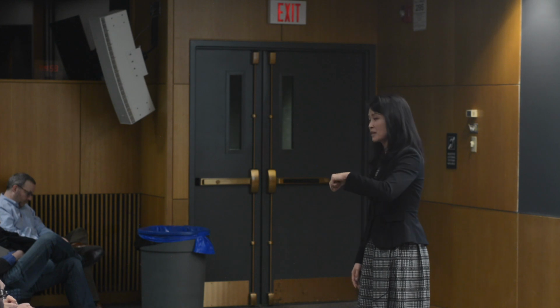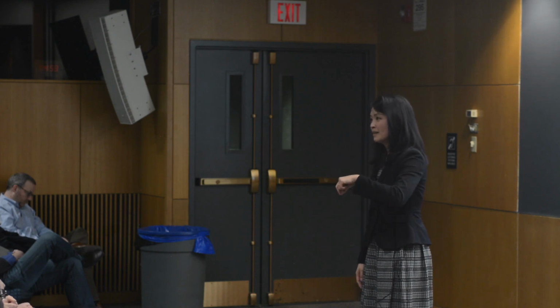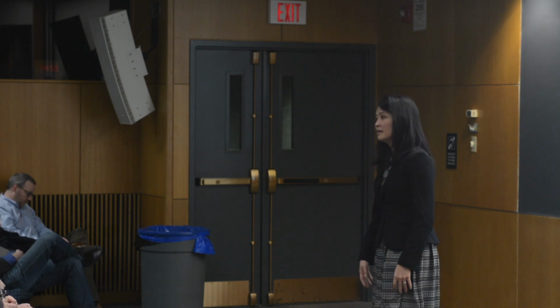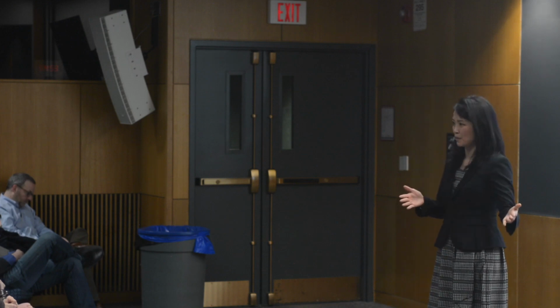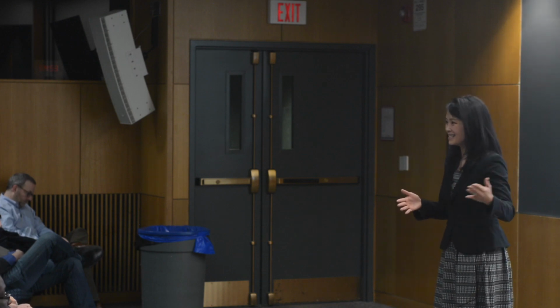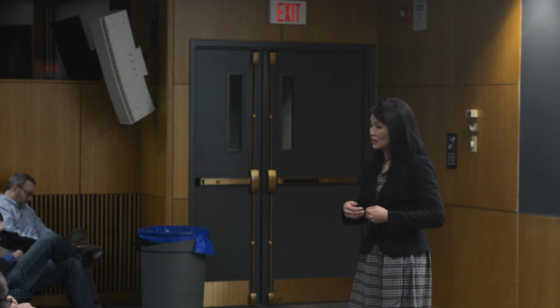And it turns out the polymorph's the same, and that was from the X-ray diffraction data. The crystal habit's different. Because, again, you're so far away from thermodynamic, it's the kinetics that matter now, and so these interactions matter. And so when you can grow fast, it grows fast. When there are interactions that block it from growing fast, it grows slowly, and you get this isotropic growth. Any questions out there?